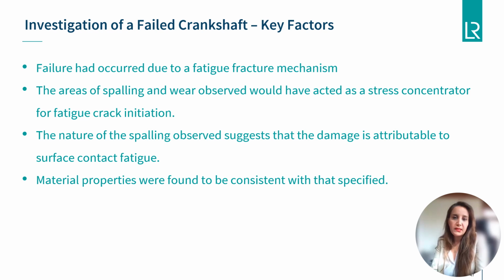So far, it was determined that the failure had occurred due to a fatigue fracture mechanism. The nature of the spalling and crack propagation suggests that the damage is attributable to sliding contact fatigue. The area of spalling and wear would have acted as a stress concentrator for fatigue crack initiation. Materials investigation also confirmed that the specified hardness has been met. Chemical and mechanical properties of the main bearing journals were found to be consistent with that specified for this material.